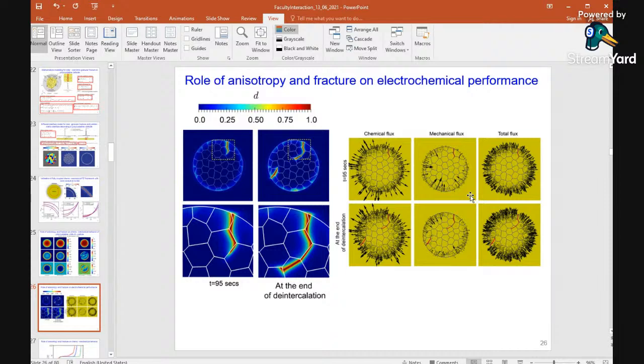You see the chemical flux is predominantly outward during the deintercalation process, which is obvious. But the mechanical flux is in the opposite direction, and this happened due to the hydrostatic stress field generated in the structure, which is trying to hold some of the lithium, giving a negative flux. And you see that when the crack has arrived, there is a discontinuity in this flux, so it is not allowing lithium to go outside in those regions, in the fracture region.